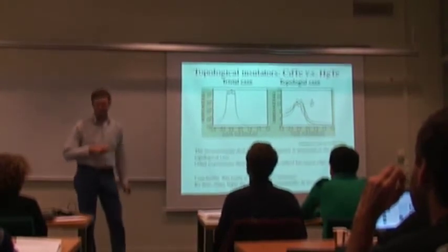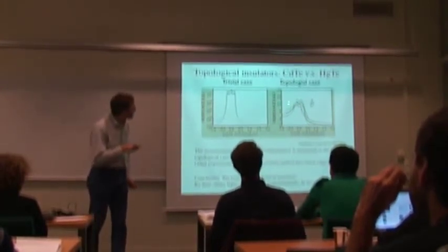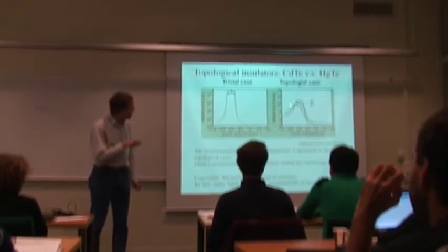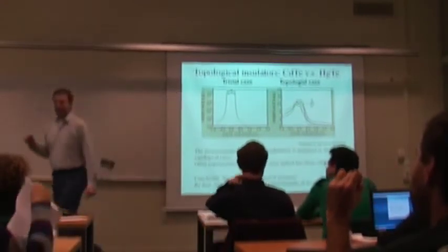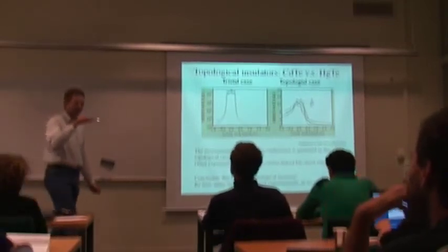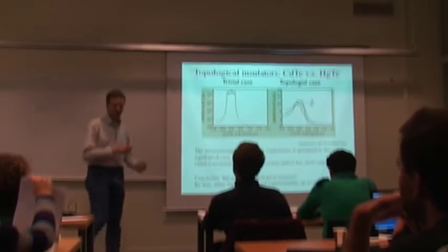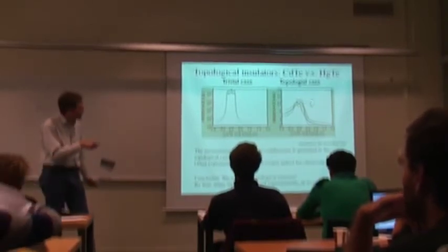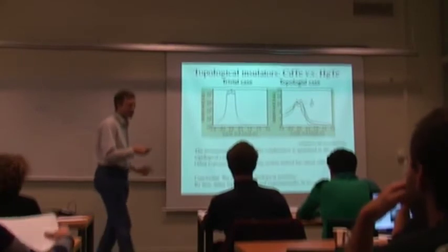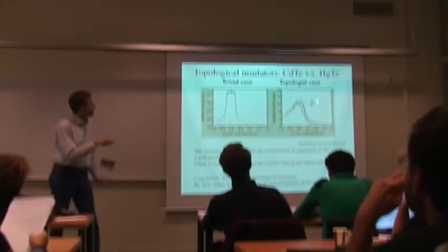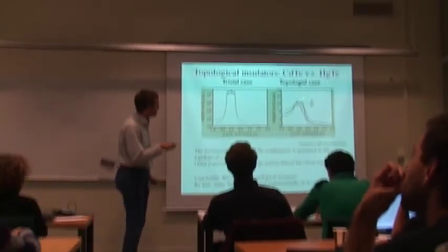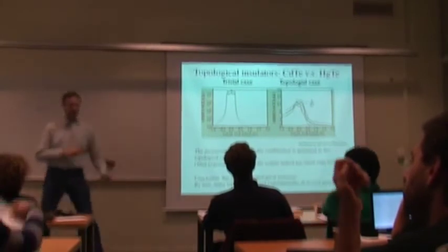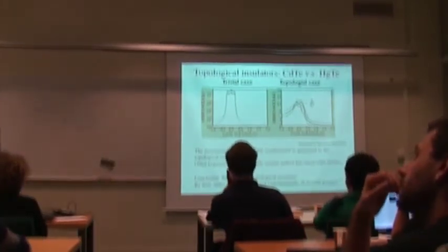And maybe I should also tell what, in the quantum Hall case, this was really quantized to a very high precision, up to this line here. Here it still looks a little murky. One of the reasons is that in the quantum Hall effect, there was really only one edge channel. But here, if I have impurities which are magnetic, that would influence these things a little bit. If I have non-magnetic impurities, this wouldn't have an effect. But if I have some magnetic impurities, then that does screw up the conductance a little bit. So one doesn't expect this to be as precise as in the quantum Hall.